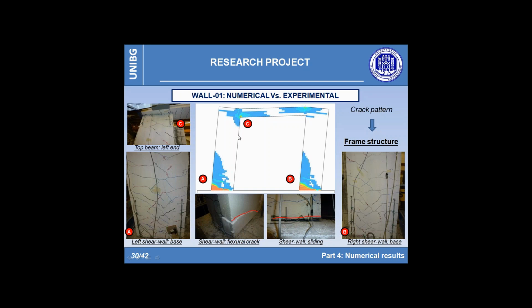The present slide, where details of the main cracks observed during the test are shown, confirms how the finite element model is able to reproduce the actual damage. In particular, in the figure, you can see the detachment at the interface between shear walls and the foundation, and also the flexural cracks at the base that have been responsible for the collapse of the structure. Both the shear walls have experienced a similar damage pattern that involves about half of the height of the wall, as shown in images A and B.